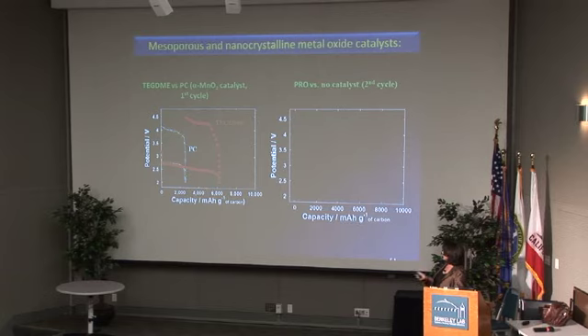So the take-home message here is that just by changing the solvent, you can increase the capacity even for a poorly functioning system. And it's poorly functioning because, as you can see, although it oxidizes those nasty decomposition products in PC, it really doesn't do it very well in TEG-DME at all. You have to go to high potentials to get that peroxide to oxidize.